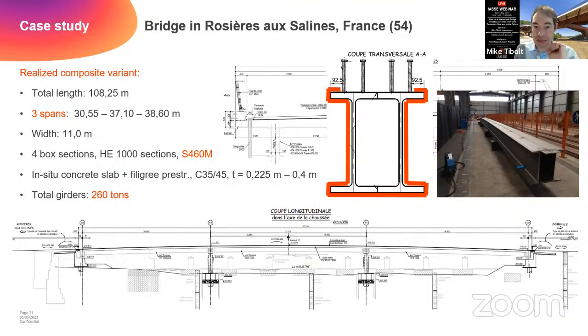My colleague Tobias Lehnert will also give a small insight into why it is useful to use high-strength steel, because also the material consumption of your project will be reduced. And you will have then the concrete slab, which was an in situ concrete slab based on the pre-stressed concrete filigree, so prefabricated pre-stressed concrete elements, with a variable thickness between 22 and 40 centimeters.